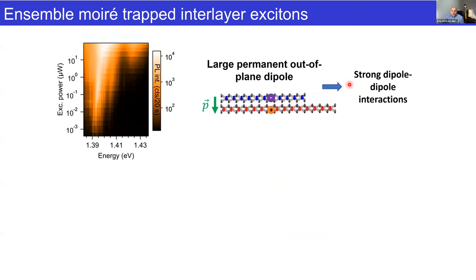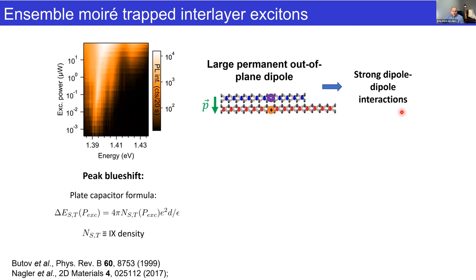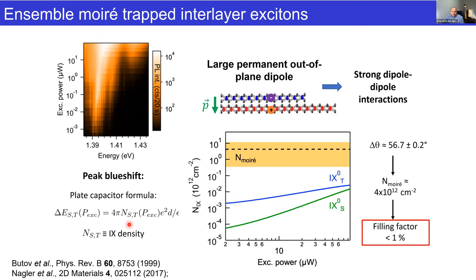As I said earlier, we have a large out-of-plane dipole for these interlayer excitons. If you look closely here, you also see a blue shift in the main peak arising, and that's due to strong dipole-dipole interactions. We can model this using work previously done on interlayer excitons from these papers here, and extract an interlayer exciton density. The rough conclusion is that for the twist angle in our sample, the Moiré density is about 100 times higher than our exciton density. So we're still essentially working with single interlayer trapped excitons. They show all the same features as when we have just single peaks, but there's an ensemble of them, and they're starting to interact, with a bit of dipolar repulsion, but in principle they're the same species of exciton.